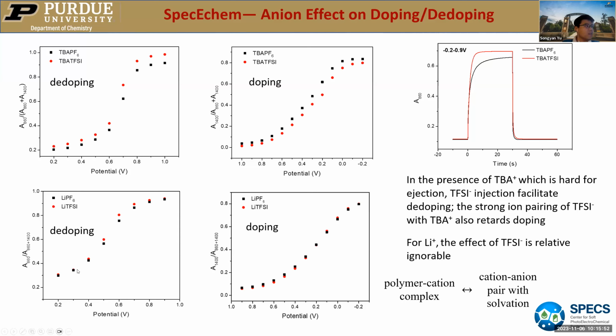So that's why I compare TBA PF6 and TBA TFSI. We can see TFSI at any potential has a higher de-doping level than PF6, and a reverse trend for the doping process. The reason is that when we have a TBA cation, which is harder for ejection, TFSI injection can facilitate the de-doping process. However, in the doping process, strong ion pairing of TFSI with TBA will retard the doping.